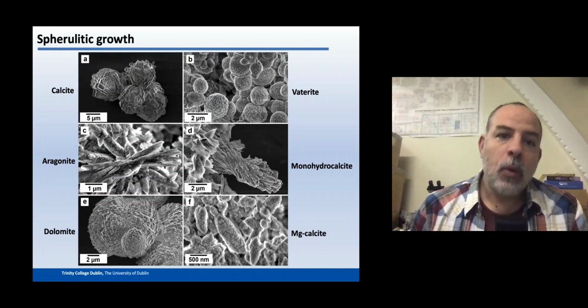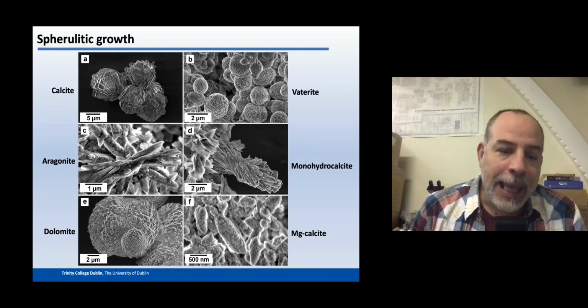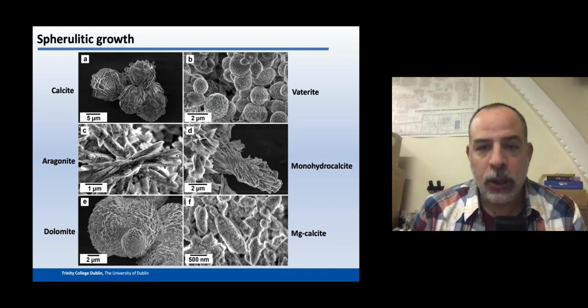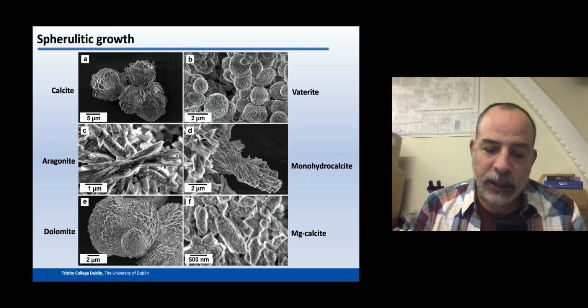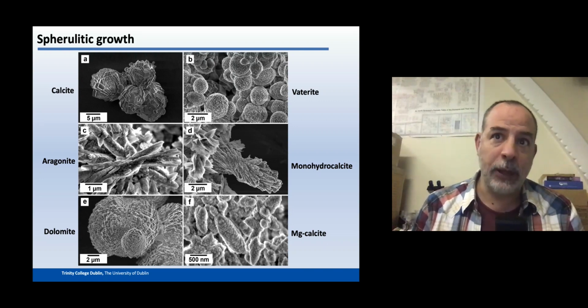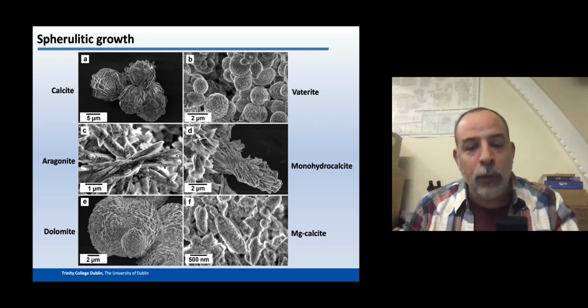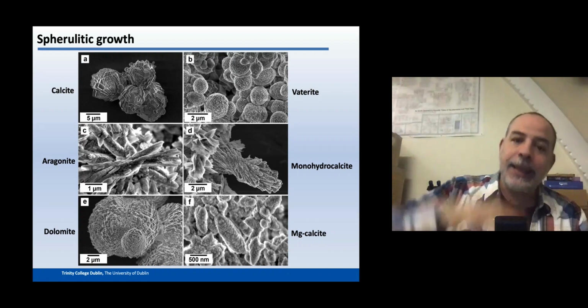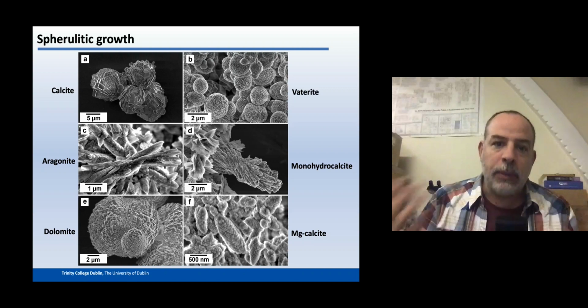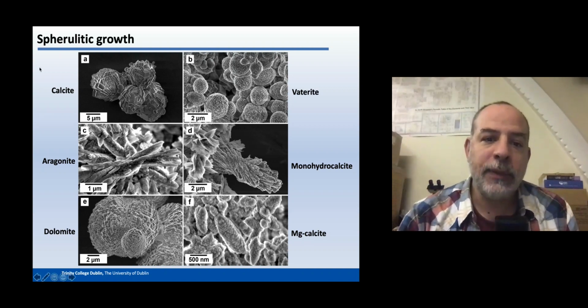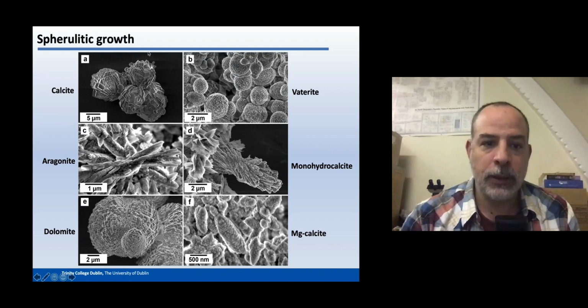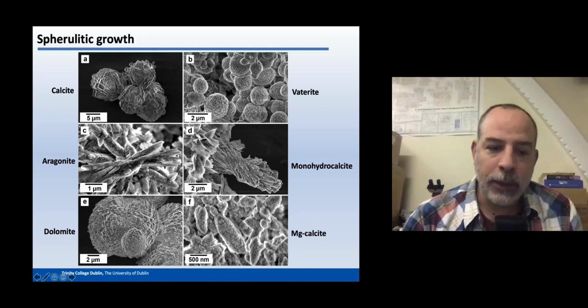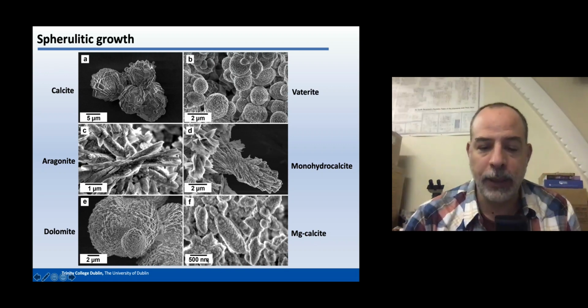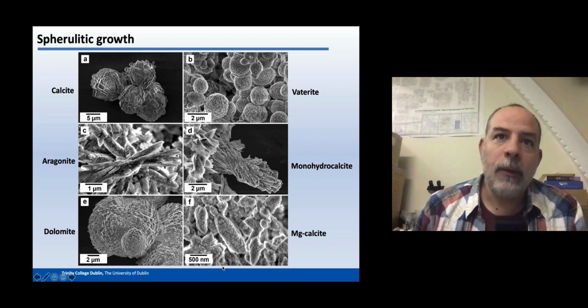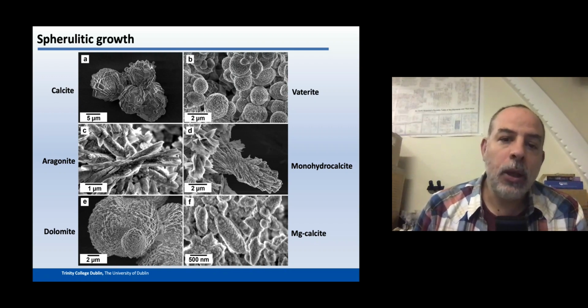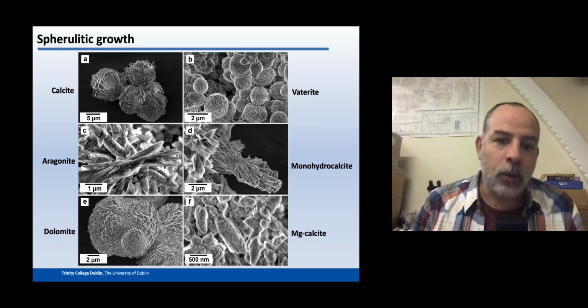What do we obtain at the end? What we have seen is that every time any carbonate forms from an amorphous phase, the first stage of crystallization is usually translated into a spherulitic growth mechanism, because the amorphous phase breaks down very quickly, increases the supersaturation levels in the solutions dramatically, and that is translated into a spherulitic growth of crystalline carbonates. And here you see some examples with calcite, aragonite, dolomite, vaterite, monohydrocalcite, and magnesium calcite. All of them have grown via spherulitic growth because of this quick decay of the amorphous phase at ambient or hydrothermal conditions.